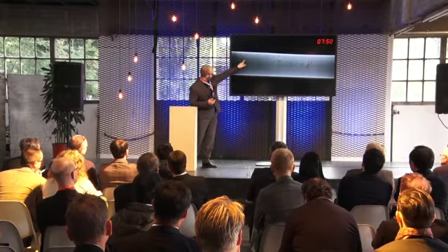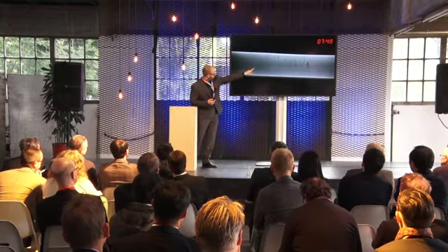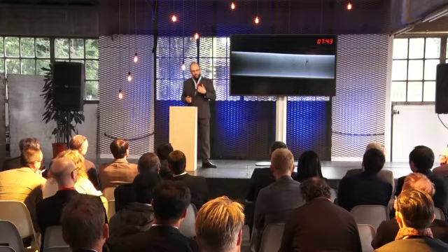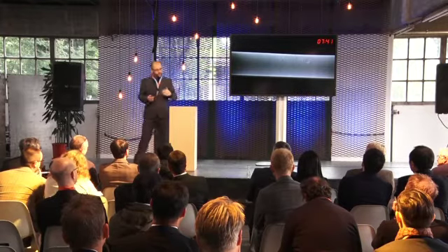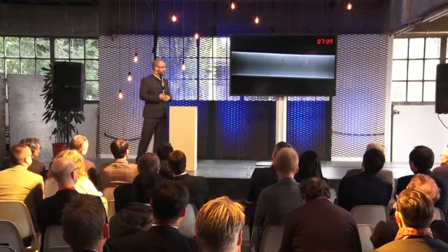So you've got the typical defect, you seem to have another one further along, and then there's a crack growing downwards. Now this area, because it wasn't particularly clear in this scan, this was actually cut out as a much smaller piece to then scan again as a higher resolution scan. And I'm just working through that at the moment just to verify how many cracks are there and how seriously they should be taken.